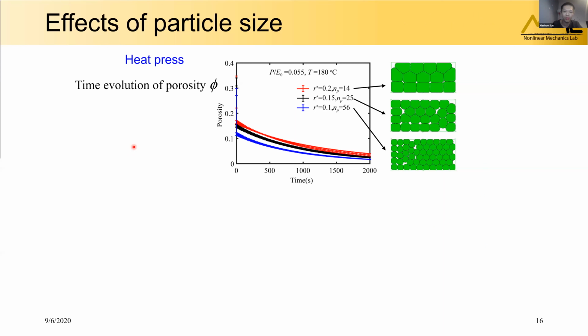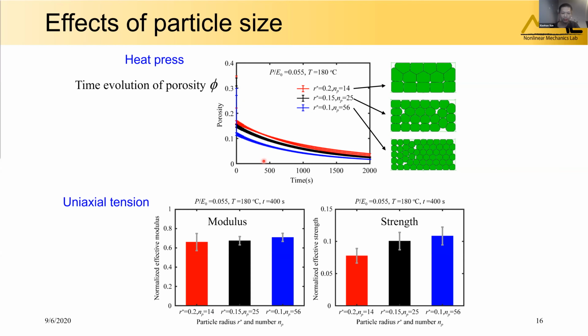So first, using the model, we study the effects of the particle size. We consider 3 cases with different particle size. For the heat press step, the 3 cases show slight differences in the time of the porosity evolution. So from the uniaxial tension step, we obtain the modulus and the tensile strength. They show no significant difference in the modulus. Such insensitivity can be simply explained by the rule of mixture that the effective modulus scales with 1 minus porosity φ. Since φ is on the order of 0.1, the effective modulus is not sensitive to its change.